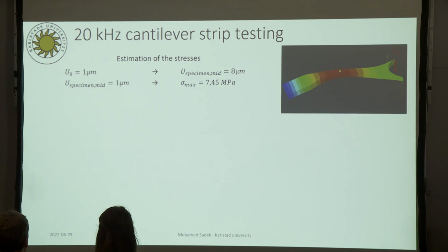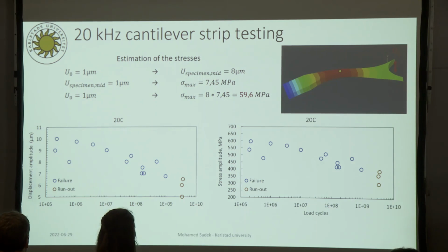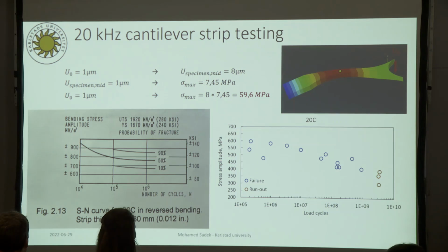And from Abaqus simulation, we could see that 1 micrometer of displacement in the middle corresponds to 7.45 megapascal stresses in the same point, same region. And then finally, we can finalize our assumption, a very simple assumption, that 1 micrometer in U0 will correspond to 59.6 megapascal in the middle of the specimen. And we can use that number to replace the displacement on the y-axis with stresses. And then just doing a fast comparison to old data from the same material at lower frequencies, we can see that these values are actually reasonable.